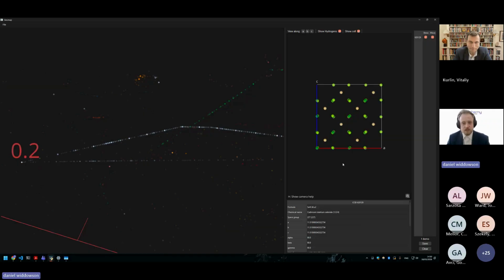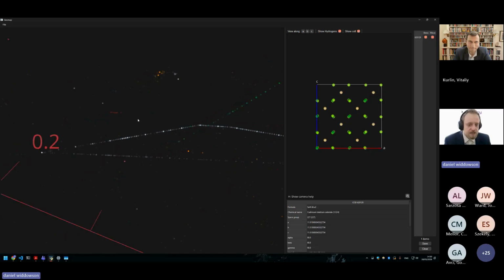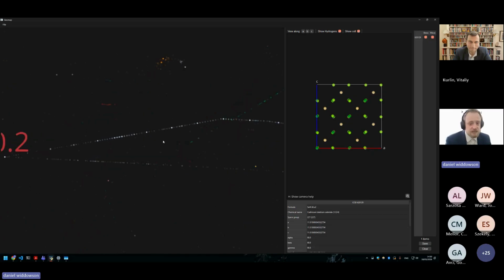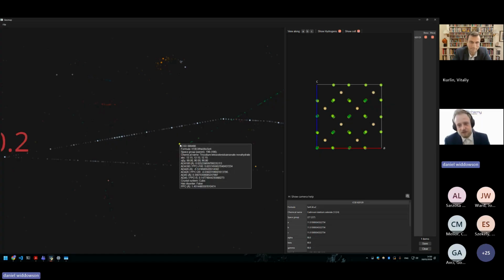And it depends on only one geometric parameter. So this is not uniform scaling, it's one atom or multiple, but they're moving and there's only one parameter you can change. They call it epsilon, and it can range from 0, which would be right over here, I think. And as you increase it, it moves along these lines. And because most CIFs write things down to 3 decimal places, that's the really hot ones you see in between. The ones that write them down to 4 decimal places are the less hot ones in between those.